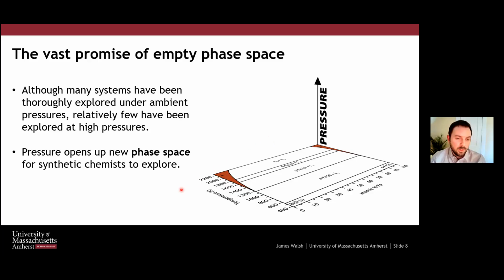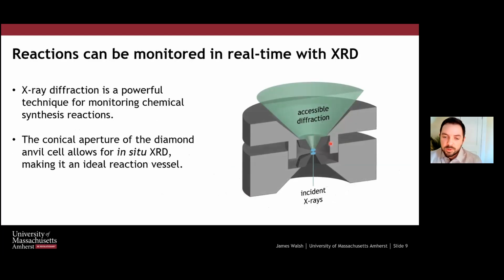So then the question is, how do we access high pressure? So if that's something that we want to explore, how do we actually do that? I think this audience does not really need an introduction to the diamond anvil cell, but one thing I do want to point out is that the ability to do in situ X-ray diffraction in the diamond anvil cell is extraordinarily powerful. And so, especially as a synthetic chemist, this allows us to, with in situ X-ray diffraction, while we're doing the reaction, monitor in real time whether we have a reaction occurring.